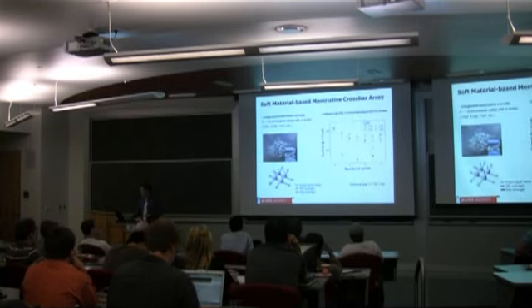and resistive. So now we reset the device, and when we come back, there's some hysteresis because of charging and also electrochemical events, but the point is, you return it back into a conductive state because you remove the oxide layer. And then of course, when you sweep it back, the oxide layer regrows and it's resistant. So if you follow that, those of you that are students, you deserve a PhD because it took me like months to figure this out. Okay, so there's the on and the off state.